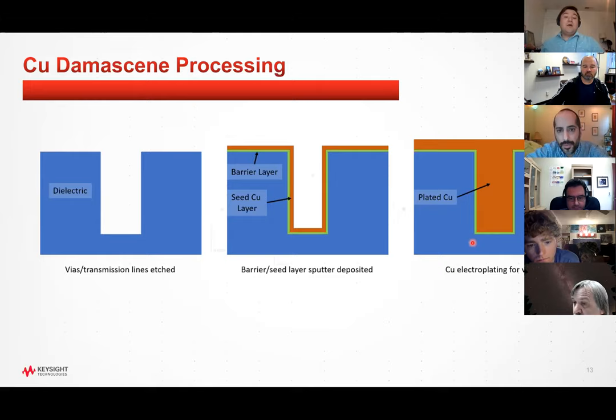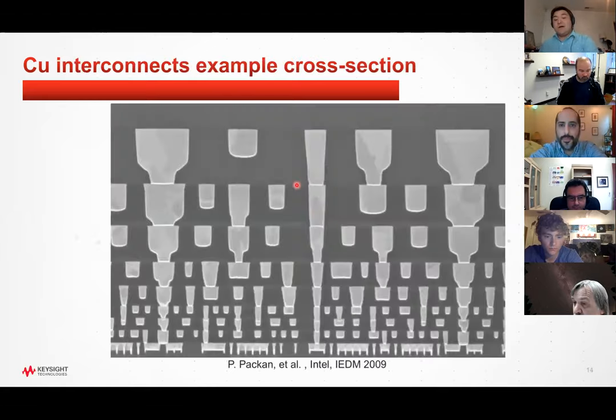And oftentimes with copper, you have to include a layer of a different material underneath, typically to help with adhesion, but also, especially if you're working with oxide, you need a diffusion barrier because copper tends to diffuse relatively easily through oxide and can cause structures to short out. So you need a material here that adheres well to copper and the dielectric and prevents the copper from diffusing out of where you want it to be.